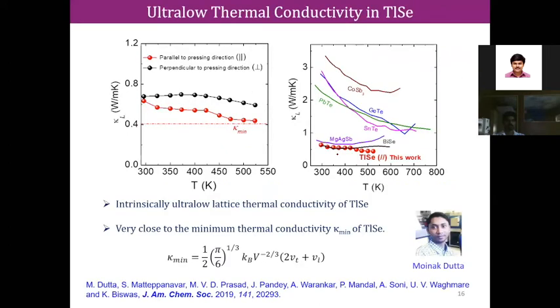Now I'll give an example from our lab, which was published in 2019. We have synthesized a compound called thallium selenide, and once we synthesized this and measured the thermal conductivity, we see an ultra low value, touching towards the theoretical minimum of thermal conductivity. It's much lower than materials like PbTe, SnTe, GeTe or skutterudite, or even Mg, Ag, Sb, which is a very famous material now, and even bismuth telluride and bismuth selenide based materials.